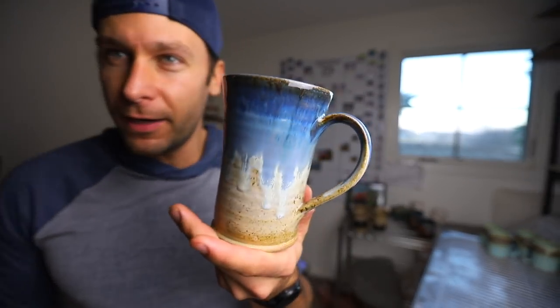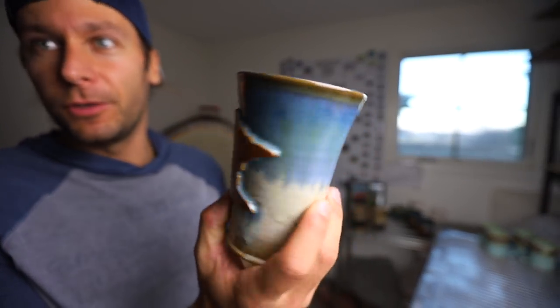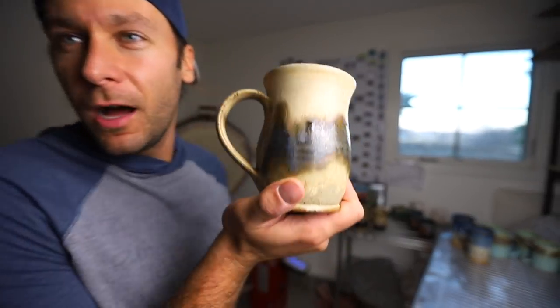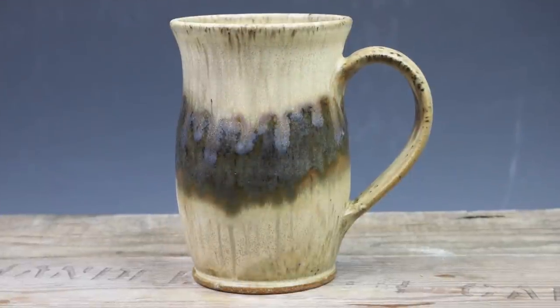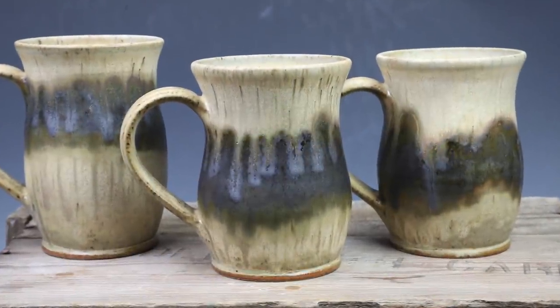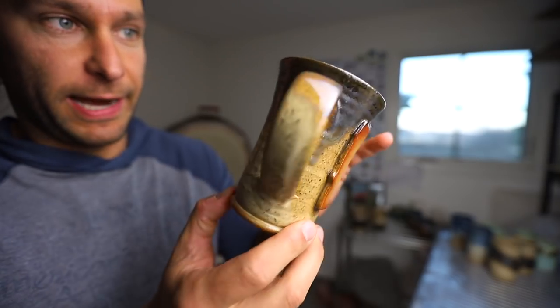Some of these were re-fired. This is midnight rain over winter wood — had a few pinholes the first time around. These are also re-fired: copper wash and then sandstone on top, and those turned out really cool. Certainly got rid of all the pinholes. That slow cool schedule is really a pinhole annihilator — usually gets rid of them pretty easily.